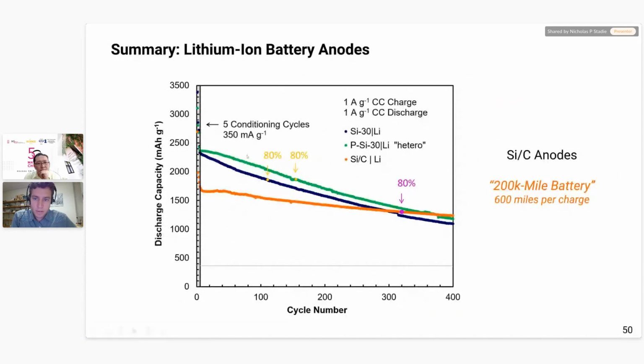Whereas on the one slide where I showed the carbon silicon composite, we have here a comparison between our best pure silicon anode and one pretty representative but standard. Again, you can tune these up and down depending on how much carbon and silicon you put in. So the ratio between carbon and silicon changes the outcome a lot. But this is just one example of a carbon silicon anode that we made in our group using a traditional CVD reaction of silane onto a carbon scaffold. And you see that you get pretty good reliability. This is nowhere near as good as graphite, but it is some decent stability.